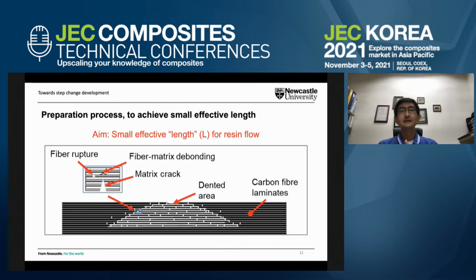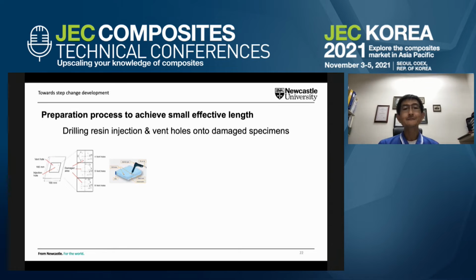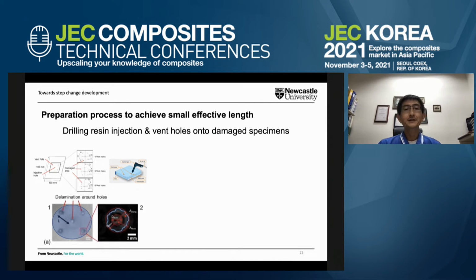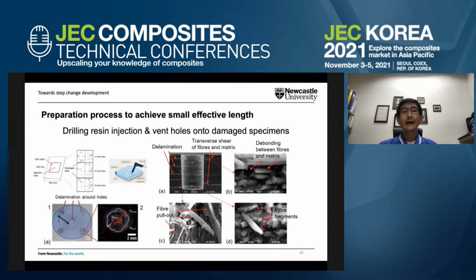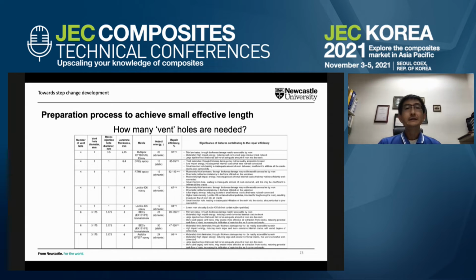But of course, developing the device is one thing. We also have to look at the processes that go into the repair. So we want to also achieve a small effective length for the resin to flow, because that contributes also to shorter time for the resin injection repair process. And this involves trying to work out, for instance, how many vent holes we should be drilling, and what's the distance between the vent hole and the resin injection holes. And we find that, as we all know, when you do drilling, you end up with local damage around the hole. And so we have to ensure that we have a way to do this very well, and also very straightforward.